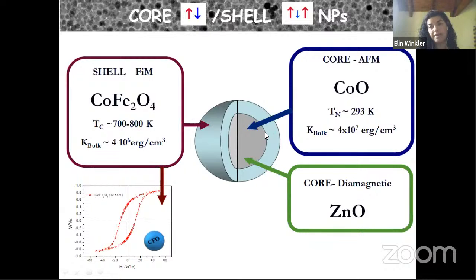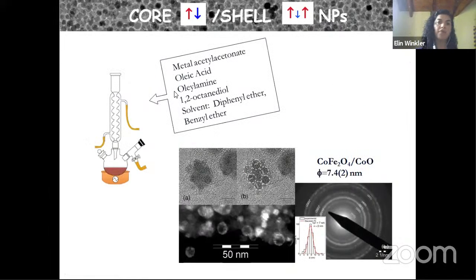So we expect that at the interface, the exchange coupling is established. And to compare how the properties of our material improve, we also fabricate another core shell system where in this case, the core of the nanoparticles is zinc oxide. The zinc, as you know, has a full last orbital, so its behavior is diamagnetic. So in this case, when the core of the nanoparticle is zinc oxide, the system won't present this exchange interaction. So we synthesize the system, first we synthesize the core, and then we use that as a seed to overgrow the shell. And here I show a core shell nanoparticle.